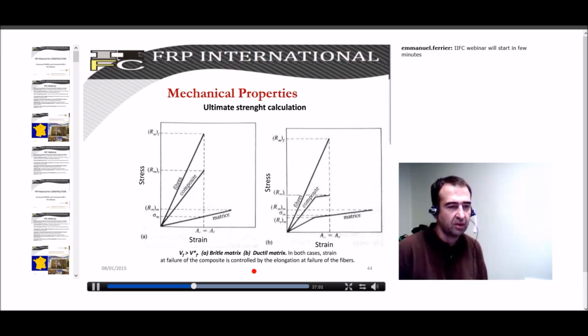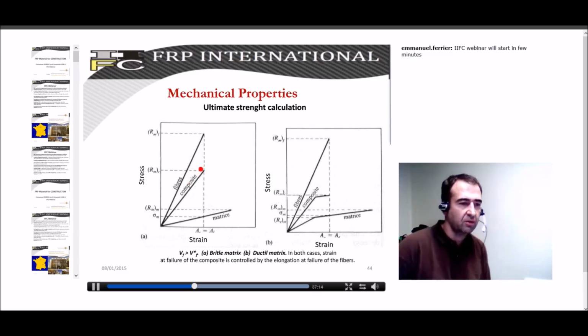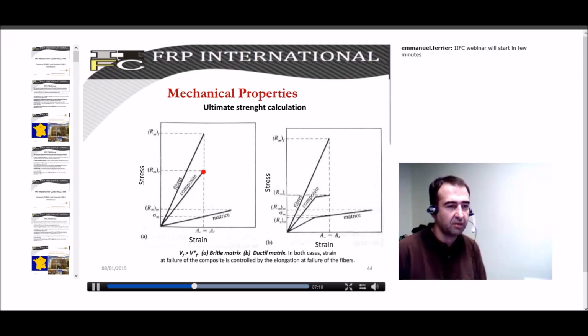So to sum up the mechanical properties, you have here the stress-strain relation in tension of fibers. Matrix, I mentioned that there is a big difference. And then if you clearly observe, you can see that the FRP material will have a final property that will depend on the amount of fibers and matrix you put, and also the initial properties of both. And for nonlinear behavior, some developments have been done in this field recently. This can be obtained depending on the matrix properties, but also on mixing fibers with different behavior.